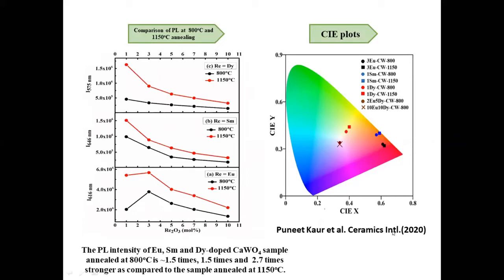So you can see this paper, and we have doped the materials with europium, dysprosium, samarium. And you can see that some of the europium doped samples lie in this region, whereas the co-doped samples containing europium and dysprosium lie in the center, which is the white region of the luminescence. So if you want white light sources, we can use calcium tungstate co-doped with europium and dysprosium ions.